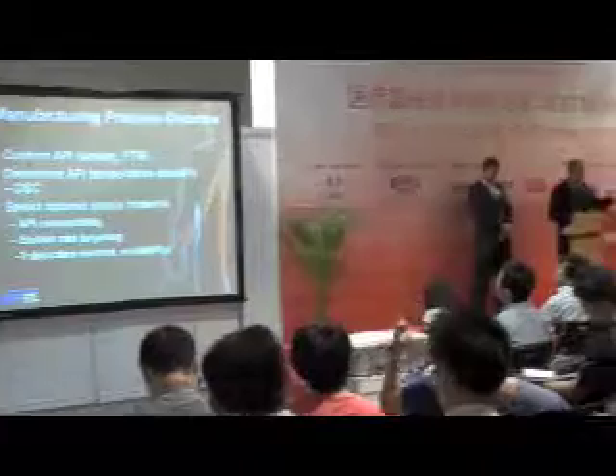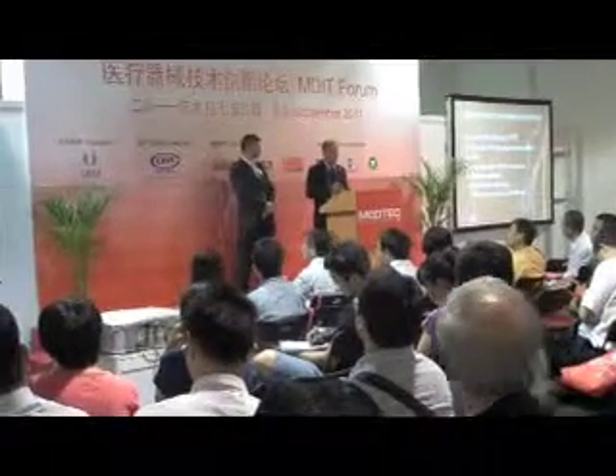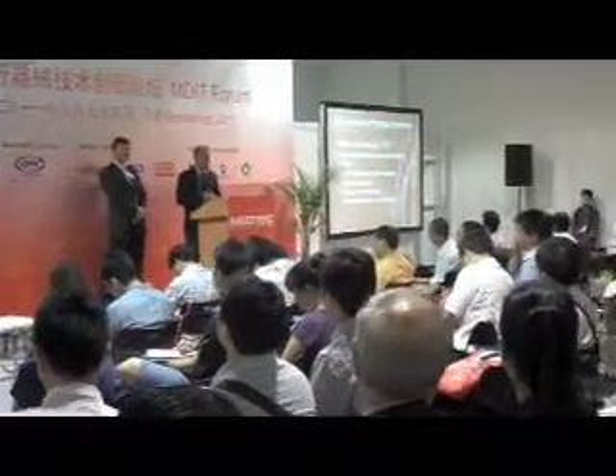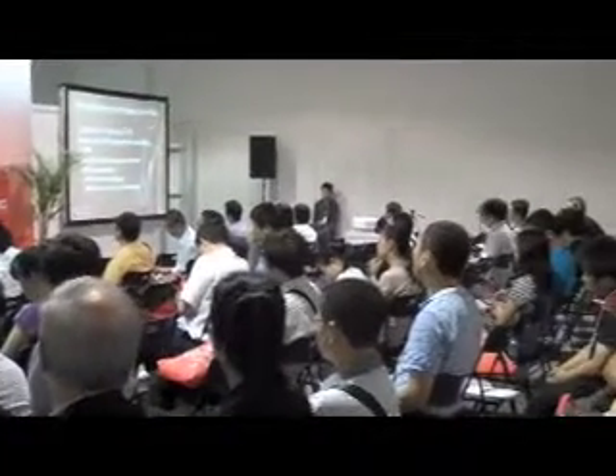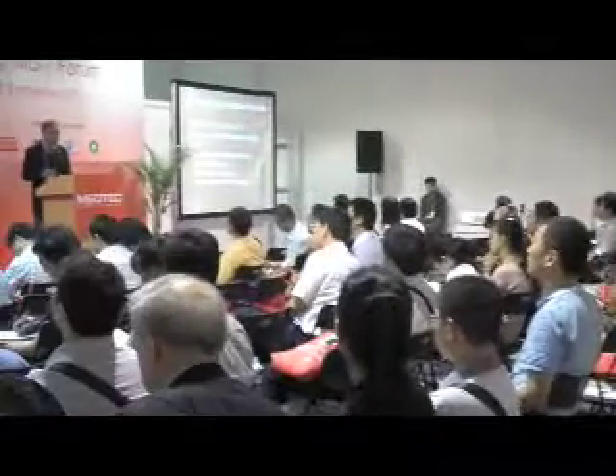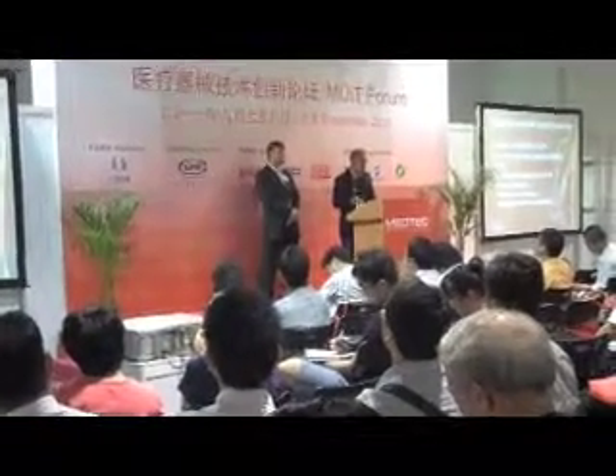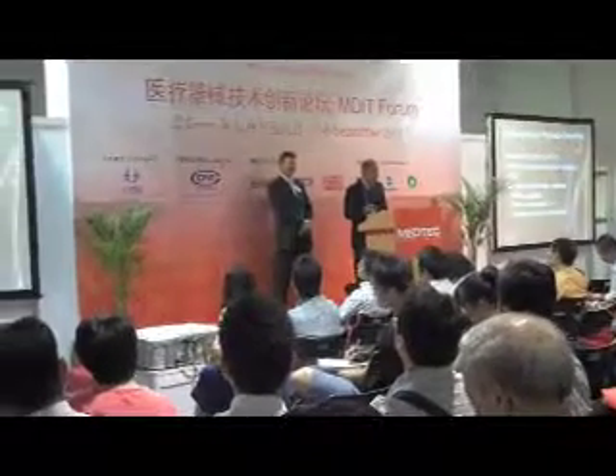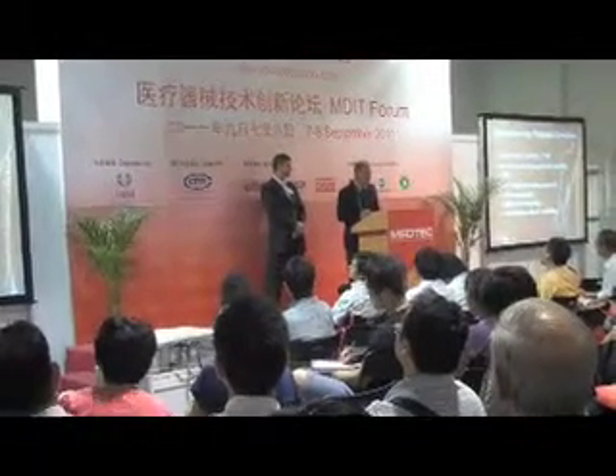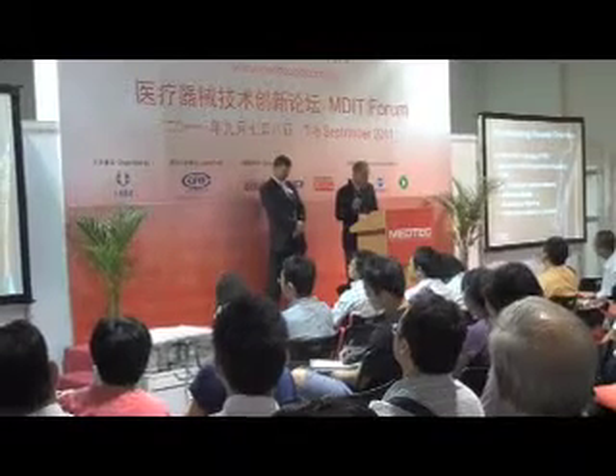Knowing the temperature stability of the drug, we then select an optimal silicone material. And again, as I suggested earlier, the two most commonly used are what are called RTVs and these platinum systems. That silicone would be chosen for several factors. Number one is API compatibility. Is the silicone compatible with the drug? Is the cure process compatible with that drug? Different silicones contain different formulations. For example, the amounts of silica would vary material to material, and that can have an impact on drug elution. So elution rate will factor into our thinking on which silicone we want to use.